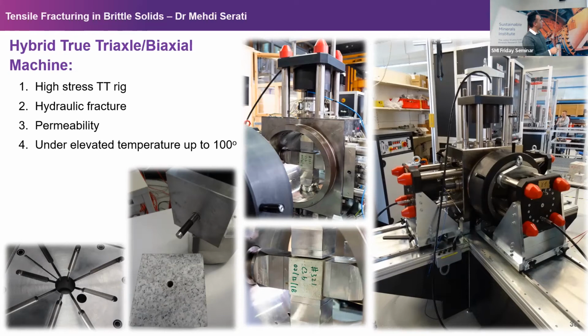We can also perform hydraulic fracturing, we can measure permeability, and we can measure behavior of rock at elevated temperature. Basically, if you have a material you're interested in developing a coupled thermohydromechanical constitutive model, I think this type of device is going to help you a lot. Here you see a concrete sample inside the cell under biaxial loading. Here you see a granite sample that has a hole, and here we have a hydraulic packer. Basically, you plug it in, and as you are loading up the sample in 3 directions, with different stresses, you can pressurize the hole up to 55 MPa, which is quite decent to understand the hydraulic fracturing behavior.